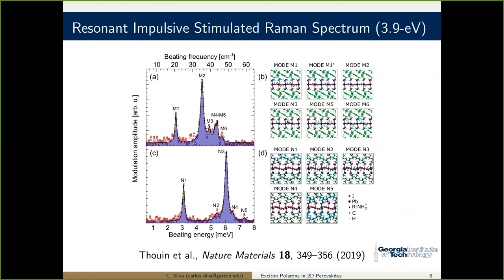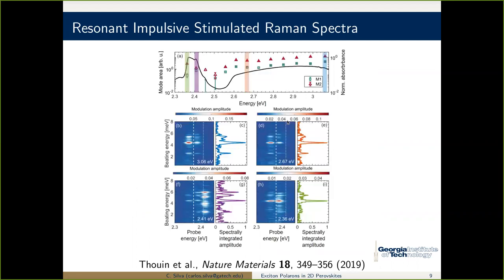Now, what we want to do is do an excitation dependence. The data that I've shown you here is exciting pretty high up here in the conduction band, so we're injecting photocarriers. And what I showed you was this sort of projection spectrum. Here are the different modes going in energy up, M1 to M6 here. This is the same thing, except that now resolved in probe energy. Remember, this is pump probe. So this is the region that we're probing around the bleach of the exciton. And these lines here are the maximum of exciton A and exciton B.